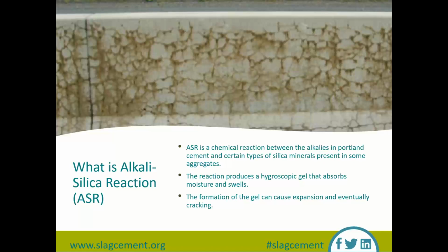This reaction produces a hygroscopic gel that absorbs moisture and swells. This swelling can cause expansion and eventually cracking in concrete. You can see an example there in the picture, and that's obviously something we do not want in our concrete. Next slide, please.